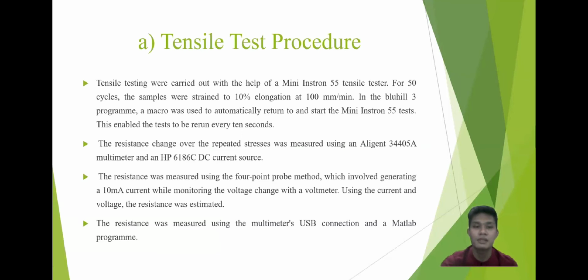The resistance change over the repeated stress was measured using an Agilent 34405A multimeter and an HP6186C DC current source. The resistance was measured using the 4-point probe method, which involved generating a 10 mA current while monitoring the voltage change with a voltmeter. Using the current and voltage, the resistance was estimated. The resistance was measured using the multimeter USB connection and a MATLAB program.